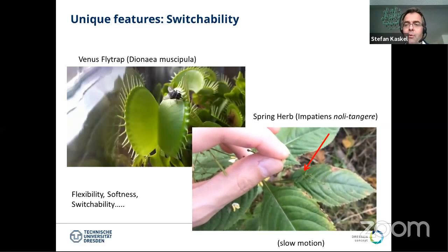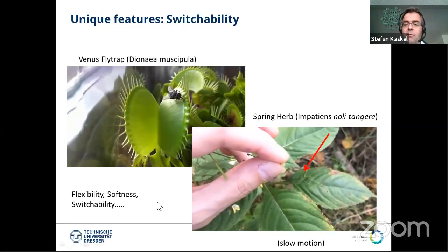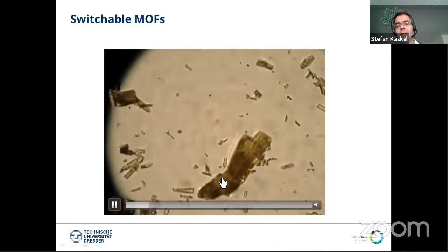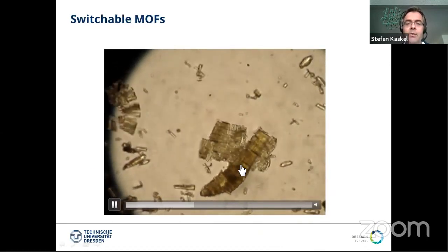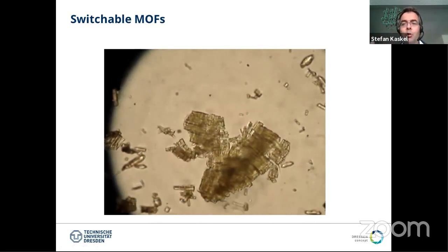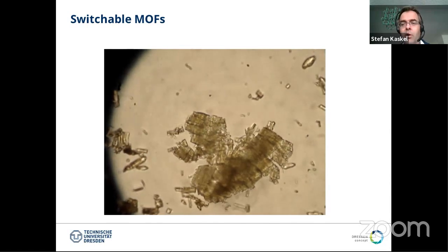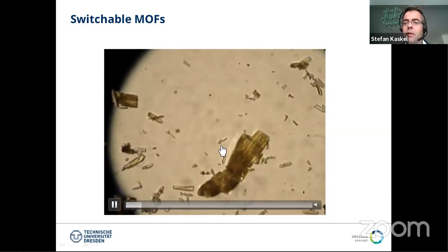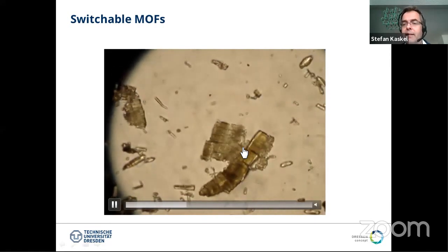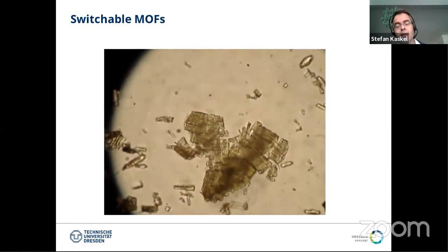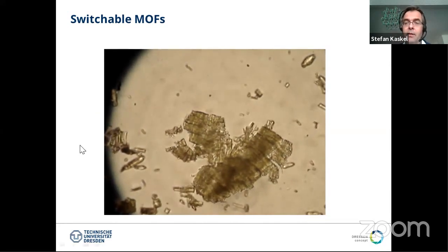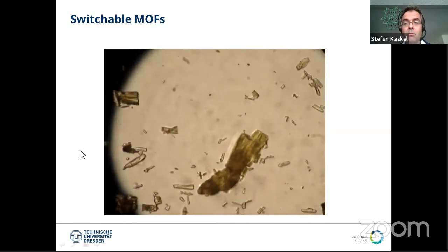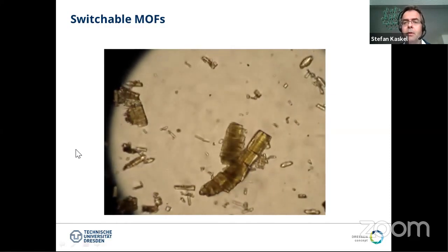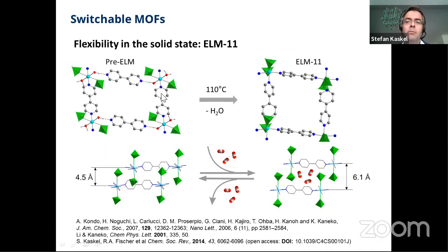And in the following, I will try to convince you that this model, the flexibility, switchability, and stimuli response, can also be a very successful model for MOFs, or at least a very interesting one. So this is a MOF that we observed and we made, and it reacts to a stimulus by showing a huge volume expansion, almost 240% volume expansion. The crystal here, when we introduce a certain guest into the MOF, and with this I would like to guide you into the field of switchability.